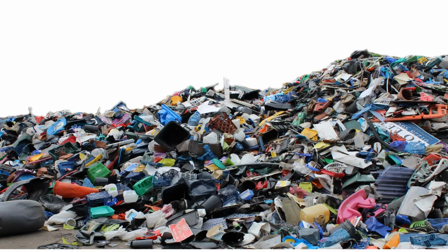This pile of plastic, as you see it here, is a mix of polypropylene, polyethylene, styrenes, all sorts of other plastics. But also, if you were to separate all the pure polyethylenes, you'd have a wide range of polyethylenes there themselves. You'd have a range of molecular weights, you'd have a range of rheologies, you have pipe grades, you have injection grades, you have extrusion blow molding grades. And it turns out that all of these grades, surprisingly, process very, very differently. And when you mix them all together, you end up with something that is a bit better than some, a bit worse than others, but in terms of processability, slap bang in the middle with no machine really suitable for processing it.